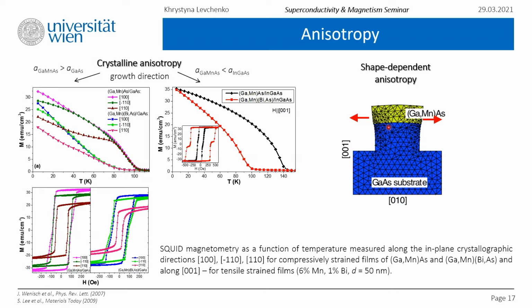And here we see one of the key limitations of gallium manganese arsenide, namely its TC, the temperature below which it's ferromagnetic, and above which it's paramagnetic, or almost non-magnetic. It's well below room temperature, which is 300 kelvins. And here we have 140 at best.